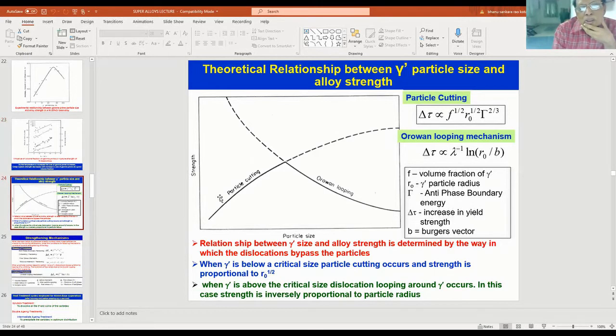Look at this. What happens? This is the same figure that I have shown earlier, now replotted as strength versus particle size. Initially with particle size, strength is increasing, and theoretically it has to go up like that, but that will not happen. After a certain peak size of gamma prime, the strength will be coming down like this. This is due to different mechanisms that are operating. When your particle size is below the critical size here, a mechanism known as the particle cutting mechanism will be operating. Gamma prime will be cut by the dislocations passing through the matrix.